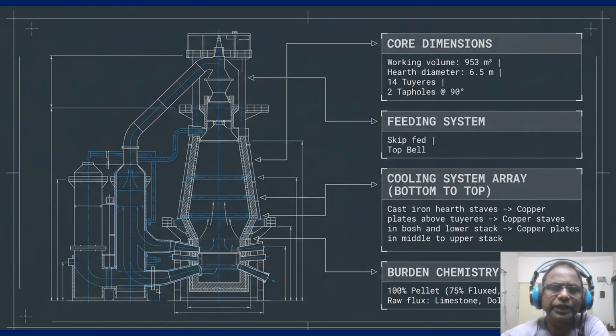So now look into this slide number 2. So we are dealing with a mid-size workhorse, a working volume of 953 cubic meter and a hearth diameter of 6.5 meter. You'll notice the cooling system array highlighted by the gray arrows. We have got cast iron staves in the heart transitioning to copper plate and staves as we move up through the Bosh and stack. This furnace utilizes 14 tuyeres and 2 tapholes positioned at 90 degree. Our burden chemistry noted in the bottom right box is a 100% pellet diet, that is 75% flux and 25% acid, supported by raw material, limestone, dolo, and other fluxes.